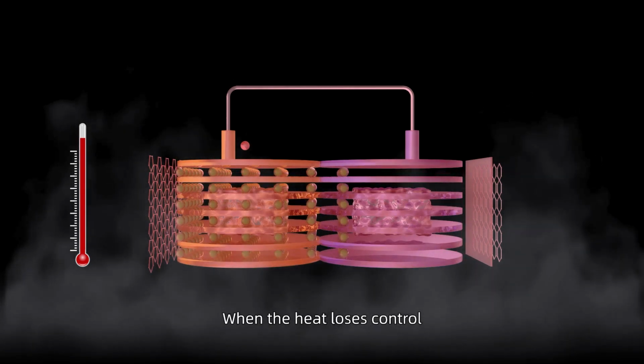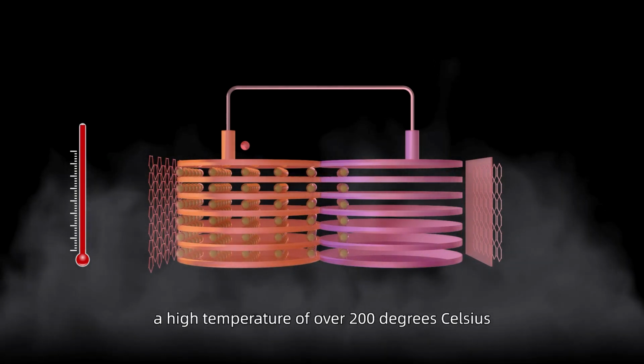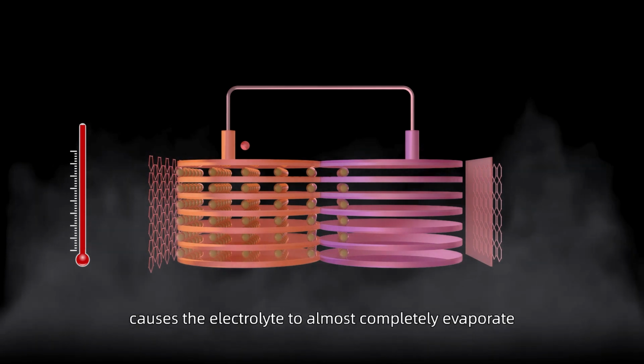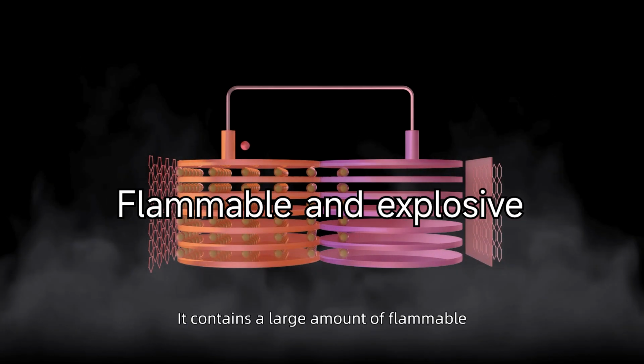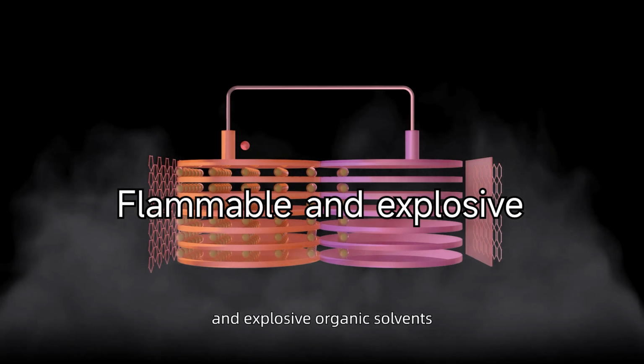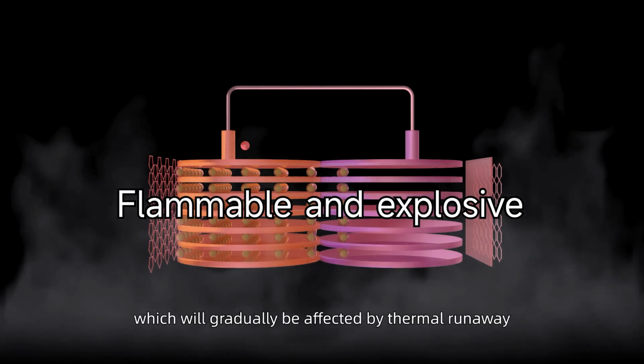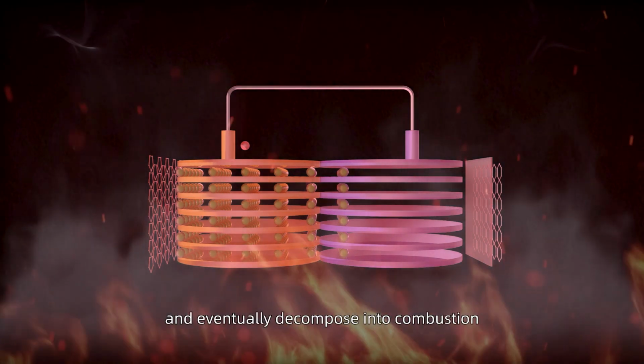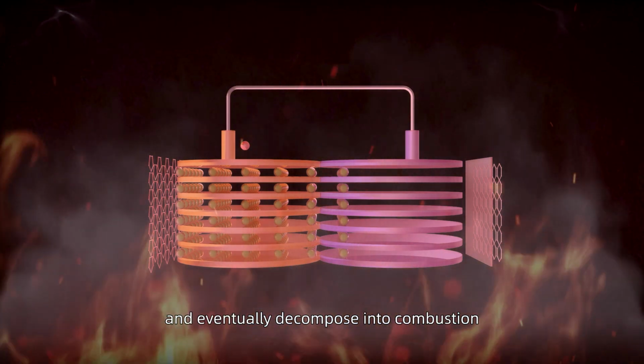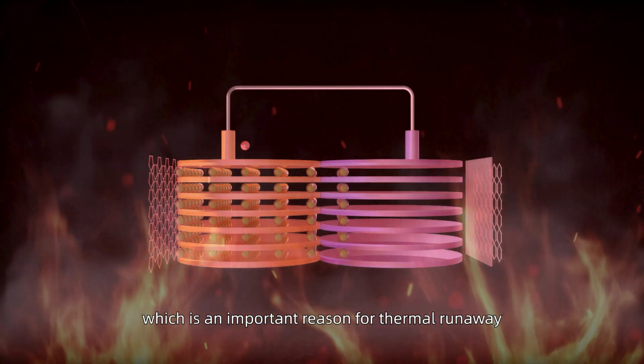When the heat loses control, a high temperature of over 200 degrees Celsius causes the electrolyte to almost completely evaporate and decompose. It contains a large amount of flammable and explosive organic solvents, which will gradually be affected by thermal runaway and eventually decompose into combustion, which is an important reason for thermal runaway.